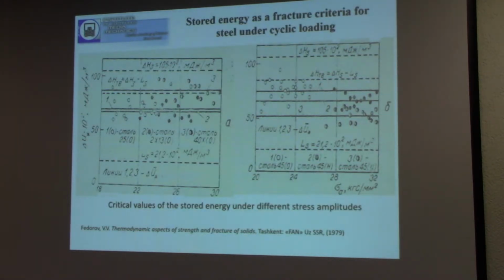We can go further, and I would like to show this picture. It's about 40 years old. It was published in Russian books, which means the results were obtained even before, about 50 years ago. This work was devoted to the thermodynamics of strength and fracture. It's not very good quality, but the general idea is that it shows different steels under cyclic loading, and the people measured the stored energy under cyclic loading and showed that fracture corresponds to the same value of stored energy. The stored energy, not dissipated, but stored, is a well-defined fracture criterion.